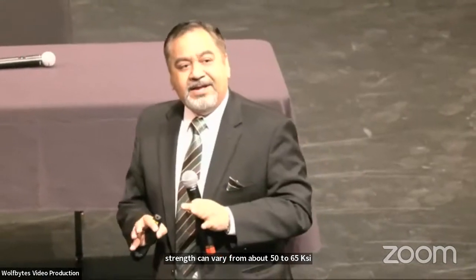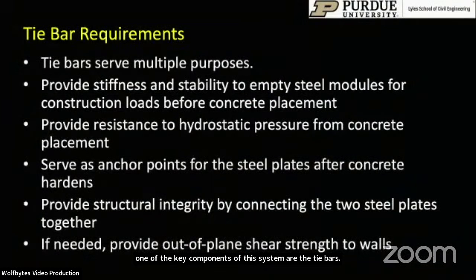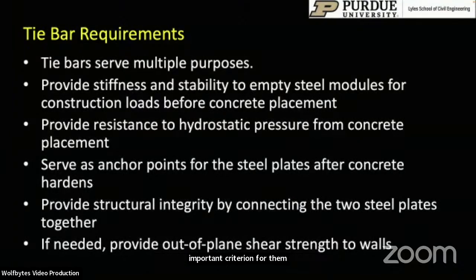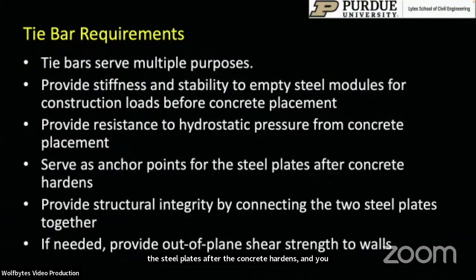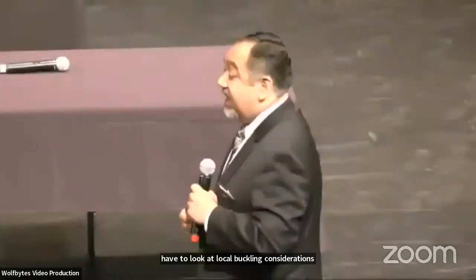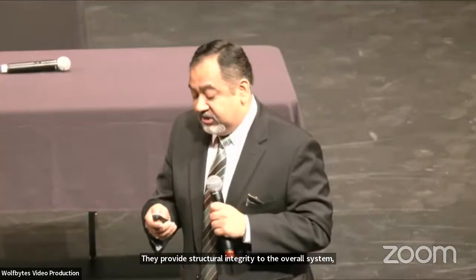Now, one of the key components of this system are the tie bars. There are hundreds of thousands of these tie bars, and they have to be connected to the steel plates. They serve multiple purposes. They provide stiffness and stability to the empty steel modules, which is an important criterion for them. They provide resistance to the hydrostatic pressure when you cast concrete. They serve as anchor points for the steel plates after the concrete hardens, and you have to look at local buckling considerations. They provide structural integrity to the overall system, and if needed, they can provide out-of-plane shear resistance as well.